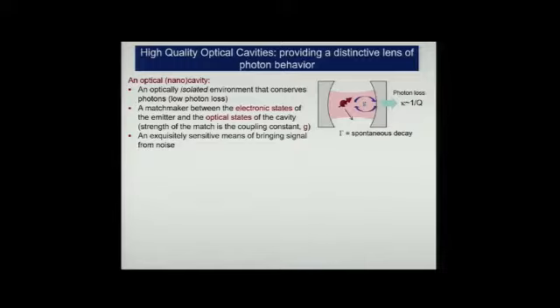A cavity is a uniquely engineered environment, and so this is what we're trying to indicate here. Here is our silicon vacancy. It's enclosed in the cavity. One way to think of it is that it's an optically isolated environment. It is that protective environment that protects our silicon vacancy from decoherence from the outside world, in particular, optical decoherence. Hopefully, the electrical decoherence is addressed appropriately by being enclosed within this large band gap semiconductor.